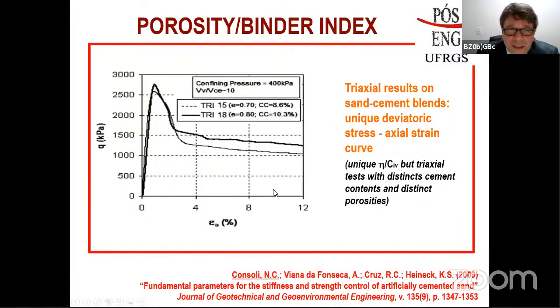Another thing from that time: we carried out triaxial tests, and we published in 2009 that if you have a unique porosity divided by volumetric cement content, you might get this value through different dosages, meaning different amounts of porosity and different amounts of cement. In this case, the volume of voids by volume of cement was 10 in these two specimens, with a void ratio of 0.7 or 0.8 and two different amounts of cement, but the ratio is the same.